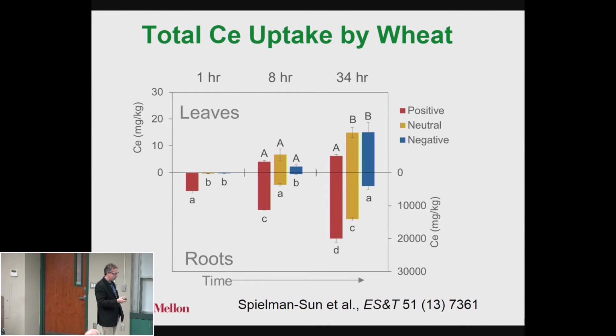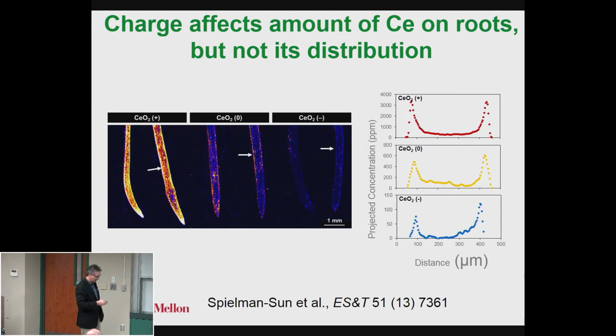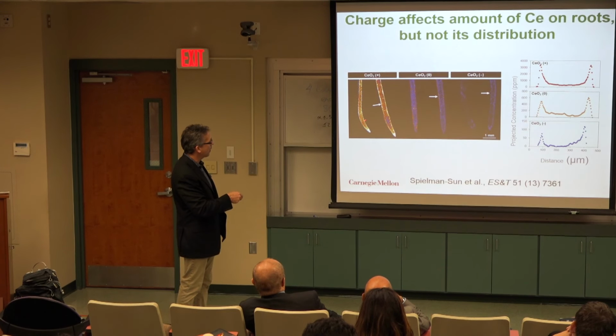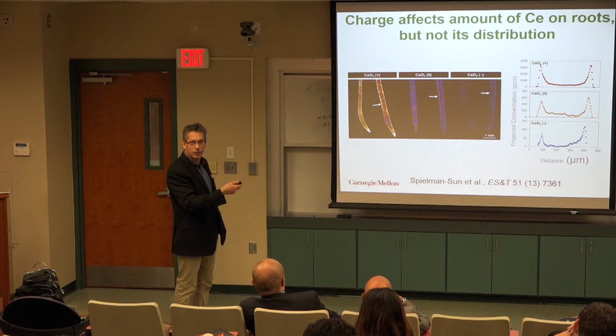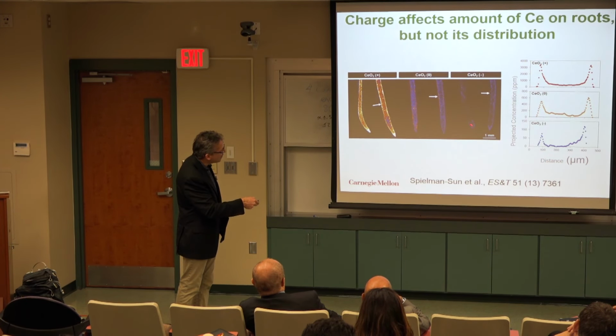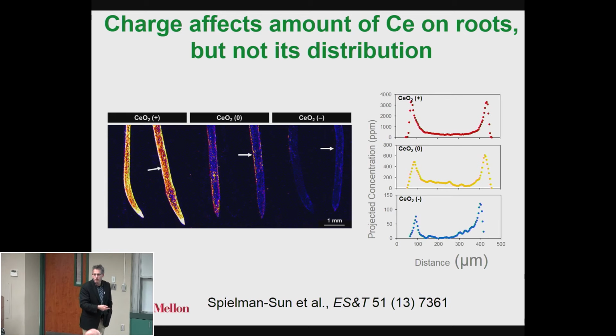So the question is, what's causing this? You know it's on the roots, and you know it's in the leaves, but you don't know where. So we start to look and we can create maps. These are maps of the roots, and the lighter colors are higher concentrations of cerium. The positive charge stuff sticks to the roots like crazy, consistent with the root studies. The neutral ones are on there and the negative ones are kind of on there. You can see them. There's enough cerium, because if there was none, this would just look black. So you can actually see the roots. And if you do cross sections, you can see the cerium is really stuck on the outside of the root. So that's interesting. It gives us a little bit of distribution.